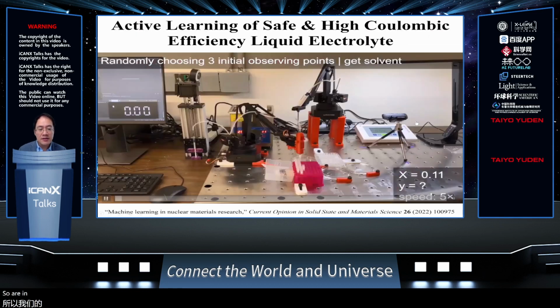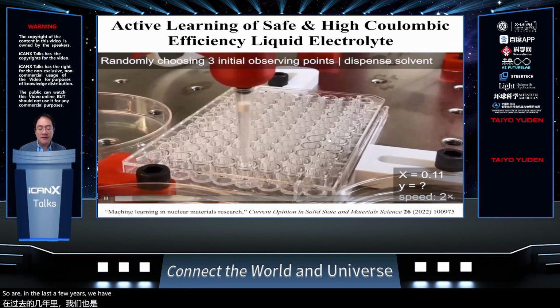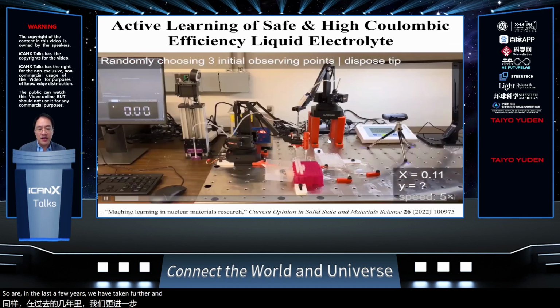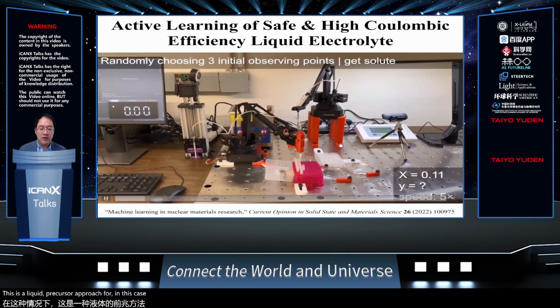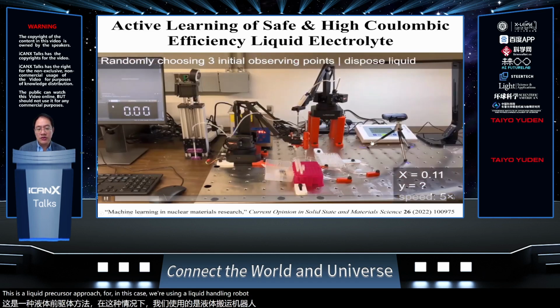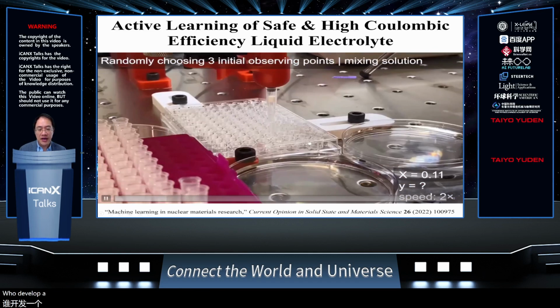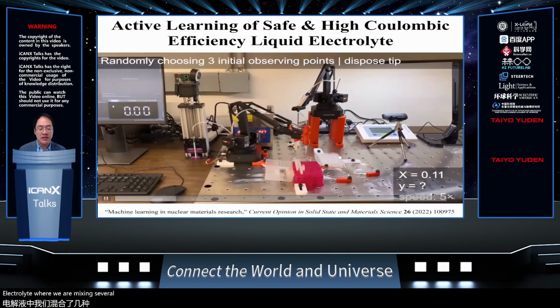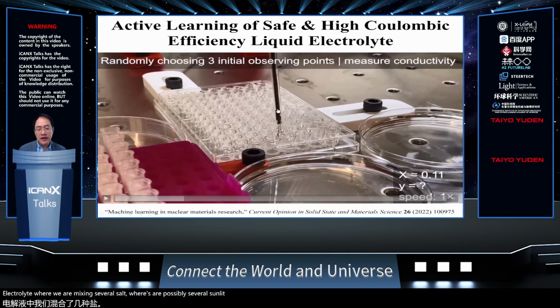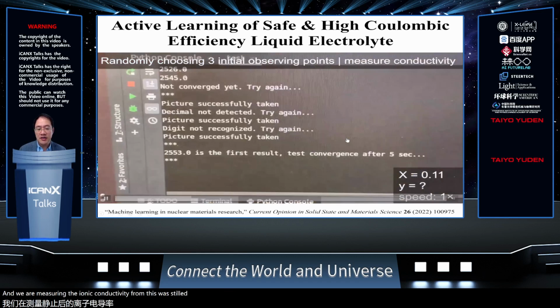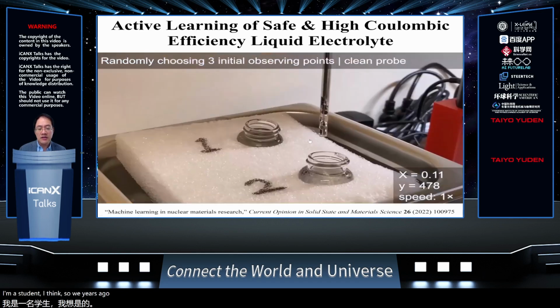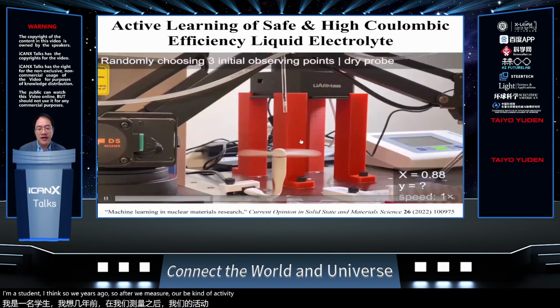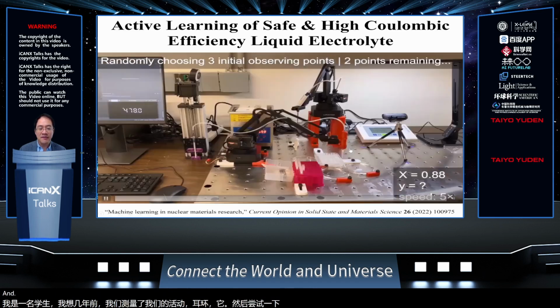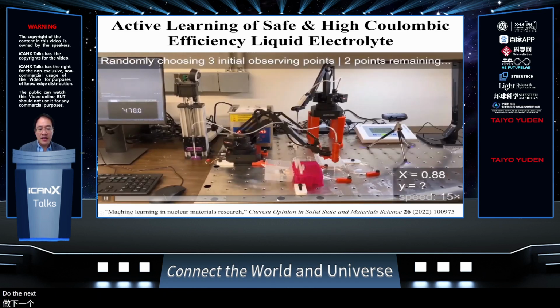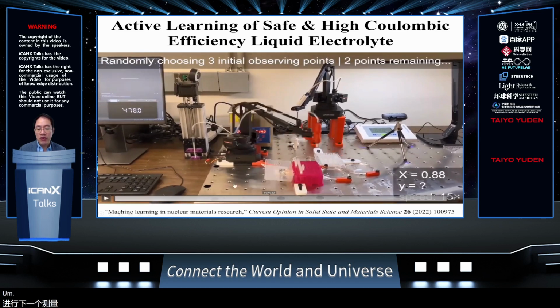So in the last few years, we have taken this further with a liquid precursor approach. In this case, we're using a liquid handling robot to develop electrolytes, where we are mixing several salts with possibly several solvents, and we are measuring the ionic conductivity. This was built by my student Zhichu Ren, I think 3 years ago. After we measure the conductivity, he rinses it and then dries it, and then does the next measurement. And so the main point is this.